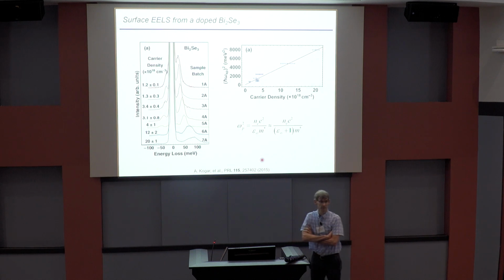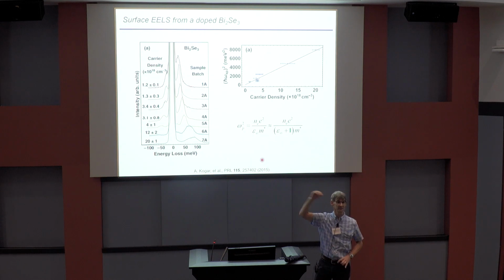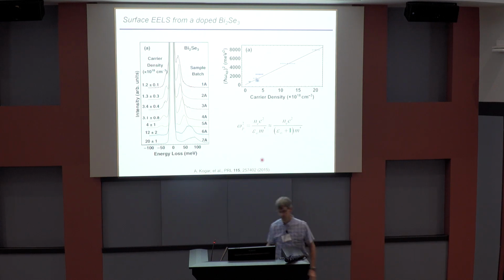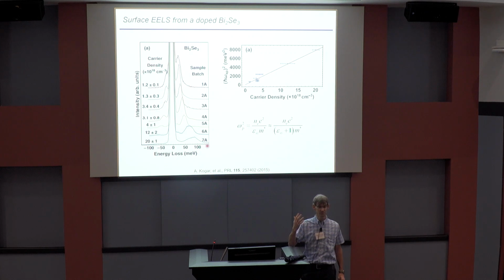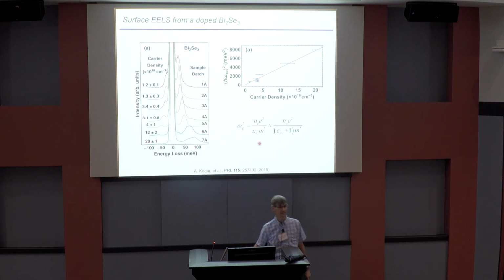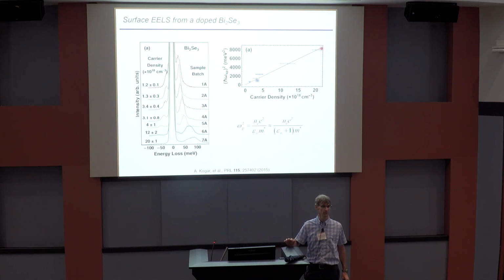So this is an EELS study from a Fermi liquid. This is doped bismuth selenide. Bismuth selenide is a topological insulator. But if you have too many selenium vacancies so that you dope electrons all the way up into the conduction band, it's basically an ordinary Fermi liquid. And if you do EELS from that, then you see a collective mode, and that collective mode is a plasmon. And the plasma frequency is this. It's N e squared over epsilon infinity m star. What we did is we took a bunch of crystals with different dopant densities, measured the carrier density with the Hall coefficient, and then you can plot the square of the plasma frequency, which is the frequency of this peak, against the carrier density. You can see that it forms a line. And the line is given by the effective mass, which you can measure with photoemission. So it all works, okay?